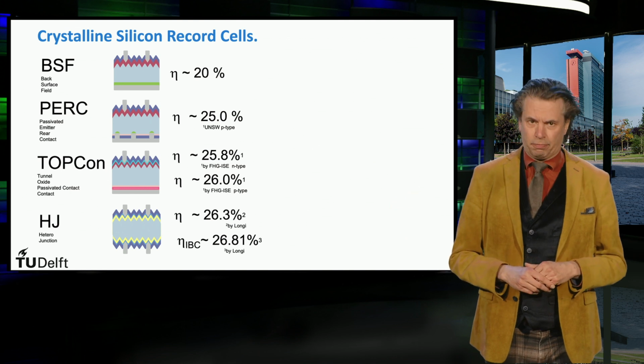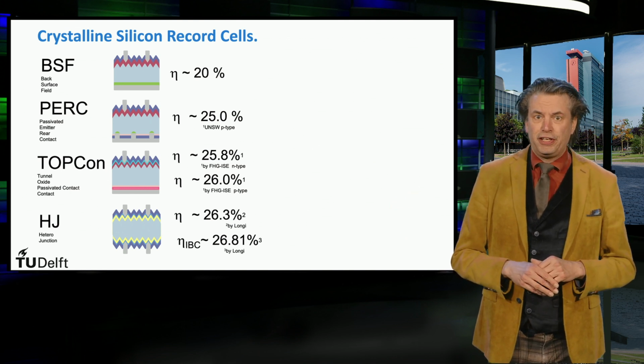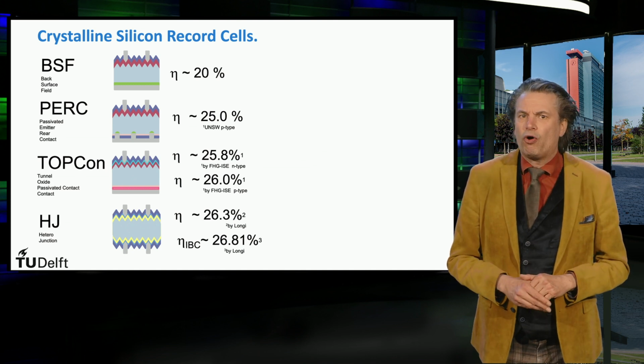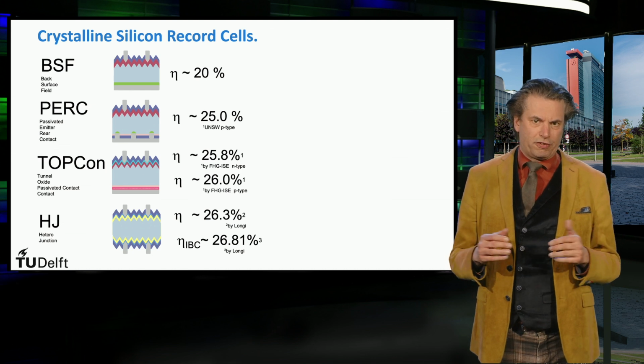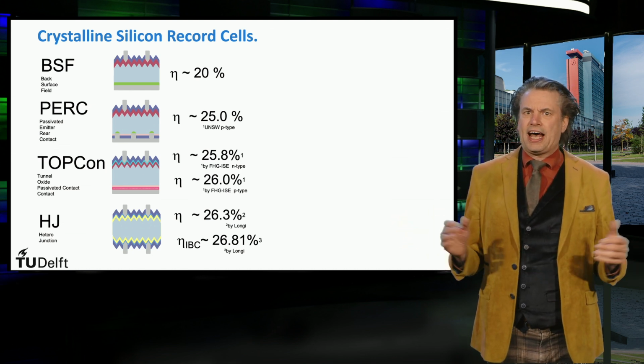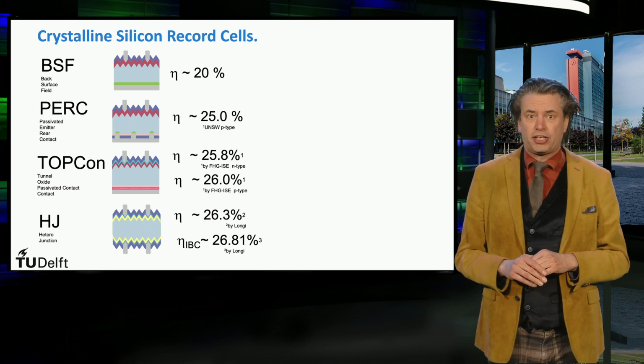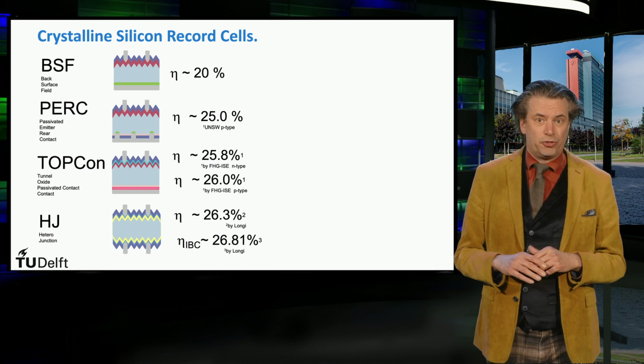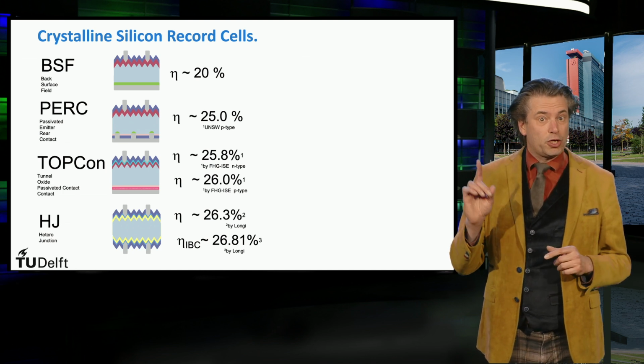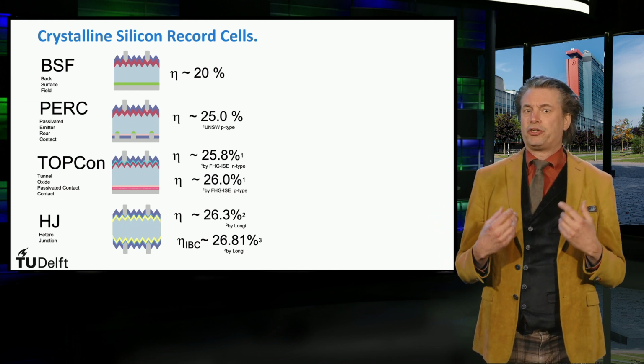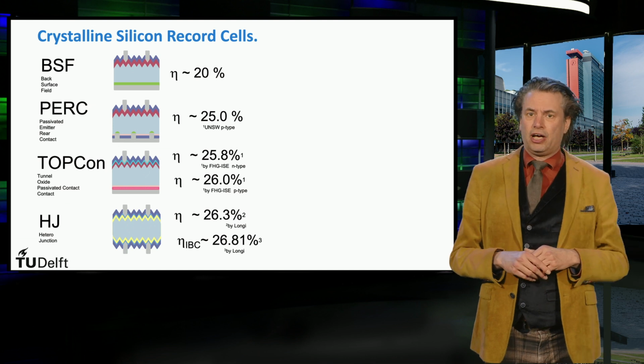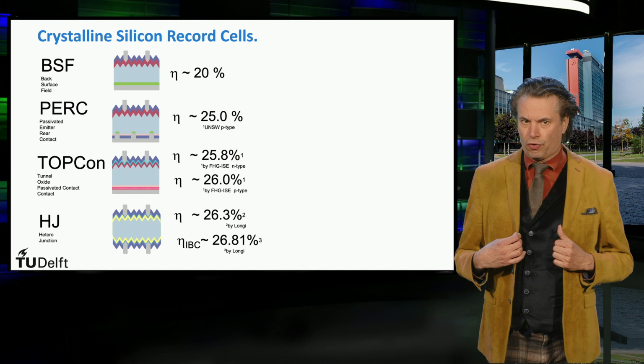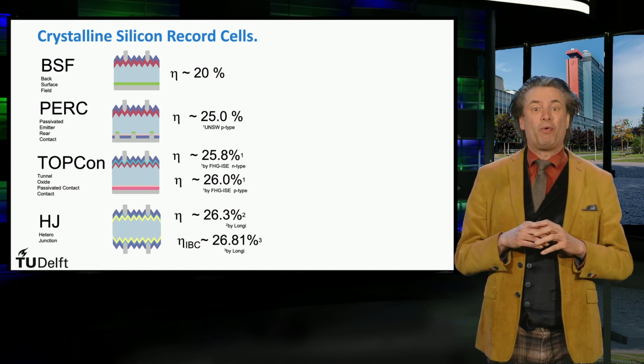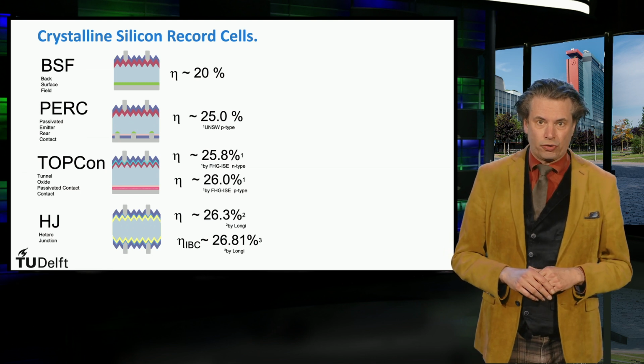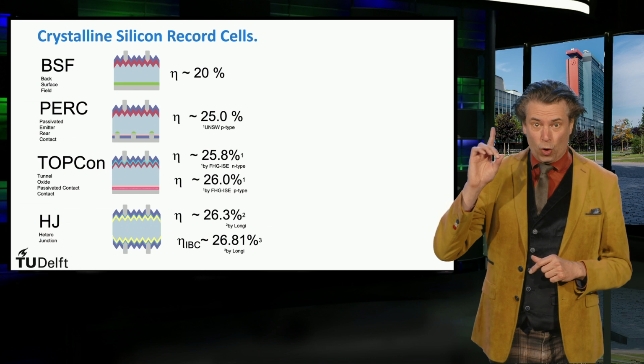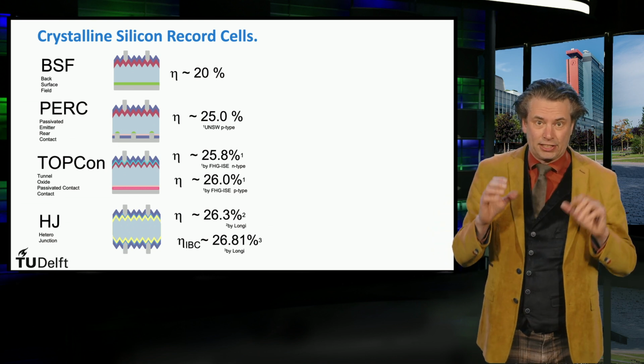Let's consider the crystalline silicon PV technology. The back surface field conversion efficiencies are in the order of 20% and the PERC is in the order of 25.0%. Fraunhofer ISE has demonstrated record efficiencies for the TOPCon concepts, 25.8% using N-type wafers and 26.0% using P-type wafers. LONGi has demonstrated the current record efficiency for heterojunction solar cells, 26.3% for a monofacial front contacted cell and 26.81% for the interdigitated back contacted cell. This is the current world record for crystalline silicon based single junction solar cells.